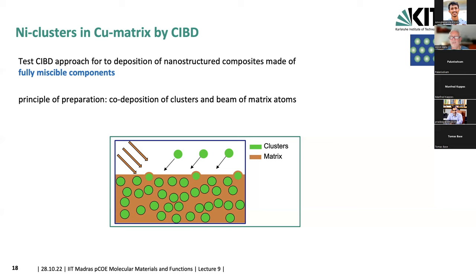And here is just highlighted again what we do. We deposit the clusters, which are preformed, and then we co-deposit the matrix, in this case the copper, from an atomic source of copper atoms, in this case an effusion cell. So this is done in parallel, and depending on the ratio of the two fluxes, we can change the composition. And we can also change, of course, the size.